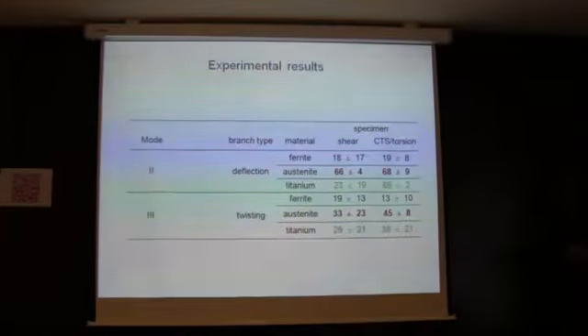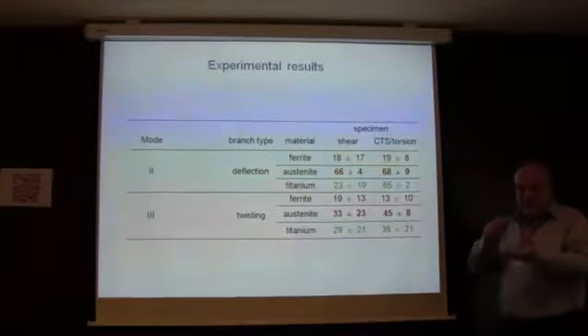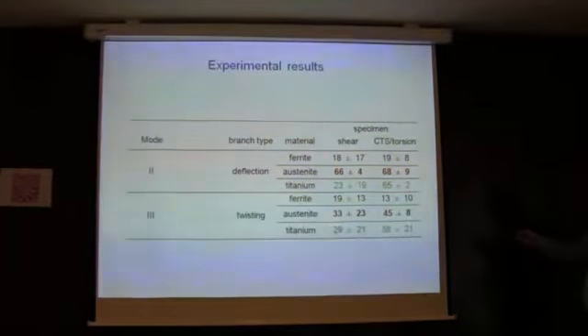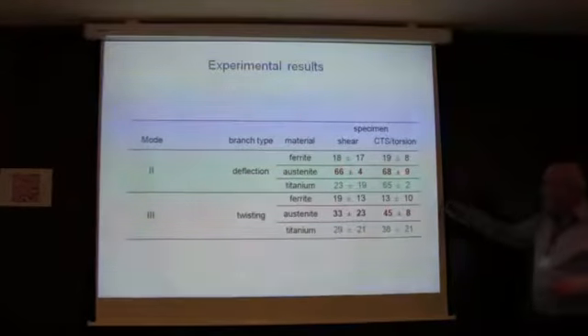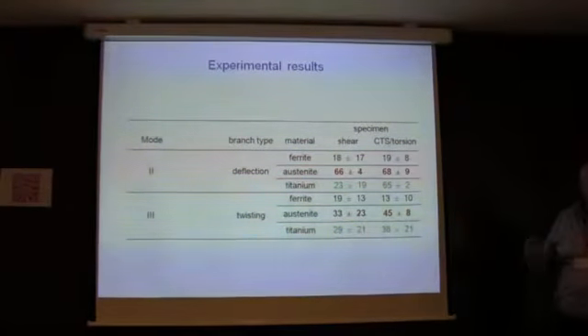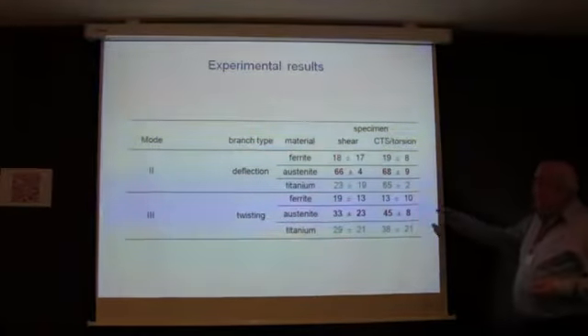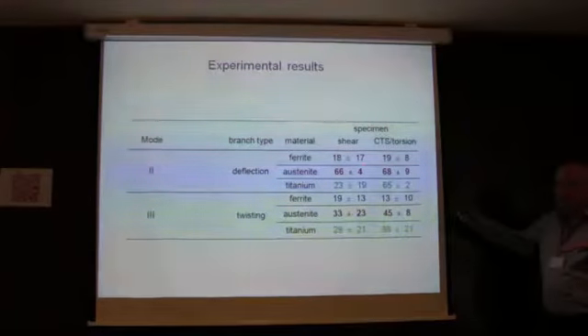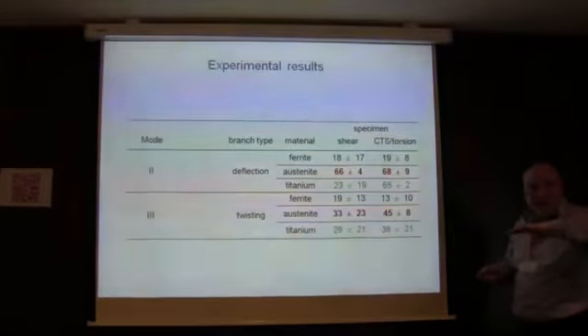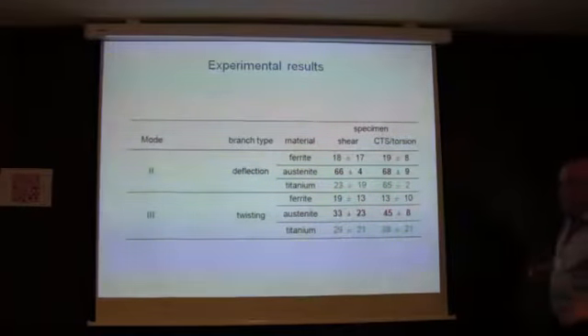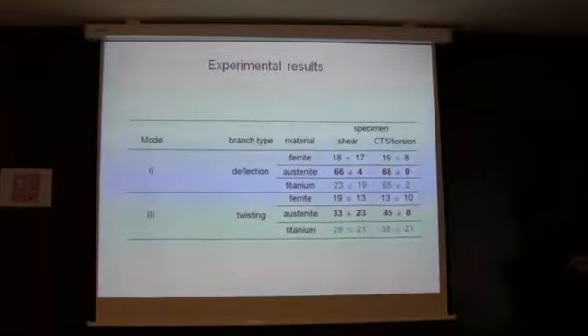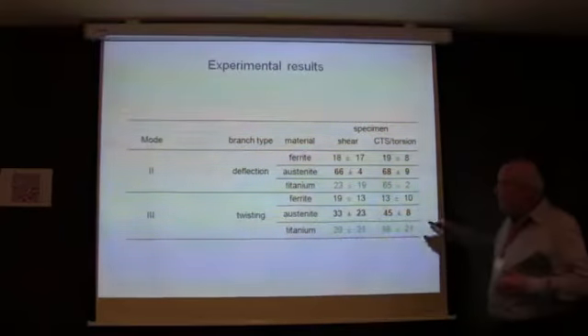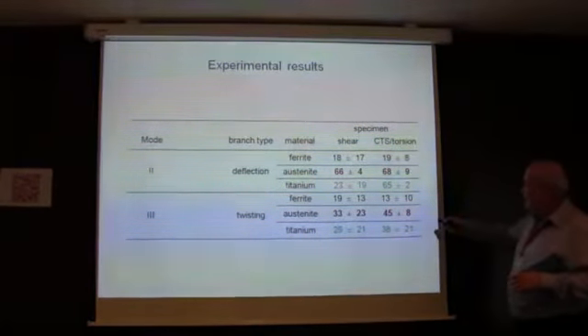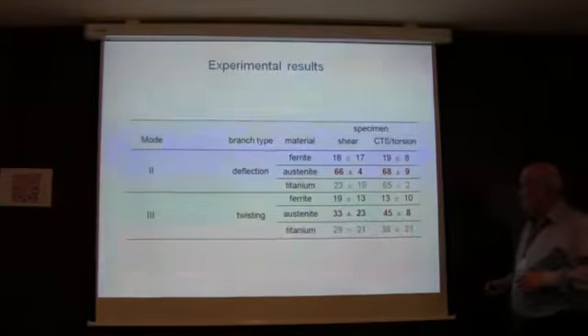Well, we also made an extended stereophotogrammetry to indicate how the crack actually propagates. In austenite, this was the case, mode 2, mode 3, deflection, twisting, very close to the theoretical value, 70%. Mode 1 branching in austenite. And in ferrite, very flat surface. Practically, the crack goes in shear mode along the maximum shear stress plane. And in titanium, there was something in between the ferrite and austenite.